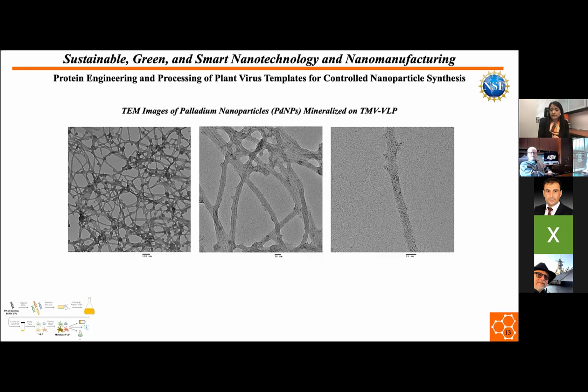And what we hypothesize is that if we use the millifluidic setup that we have developed in our lab, we can get a uniform coating of palladium nanoparticles on the surface of TMV VLP with fewer coating cycles in a millifluidic reactor compared to the batch reactor.